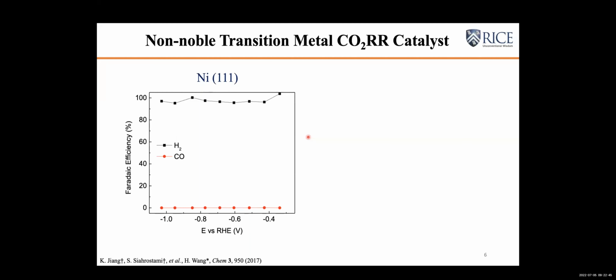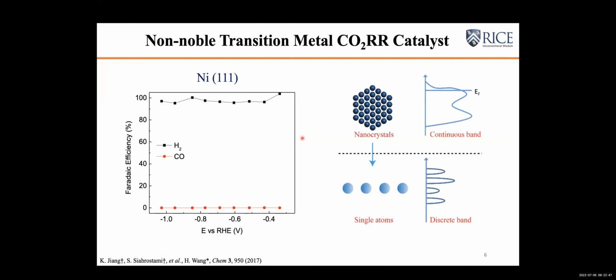So you cannot generate any CO2 reduction products. So at that time, we were thinking in a different way. We were thinking about how we can tune and change the electronic structure of the transition metals to make it possible to be a CO2 reduction catalyst. So we were thinking, what if we can further shrink the size of the nanocrystals or nanoparticles of nickel all the way down to isolated transition metal single atomic site catalyst.